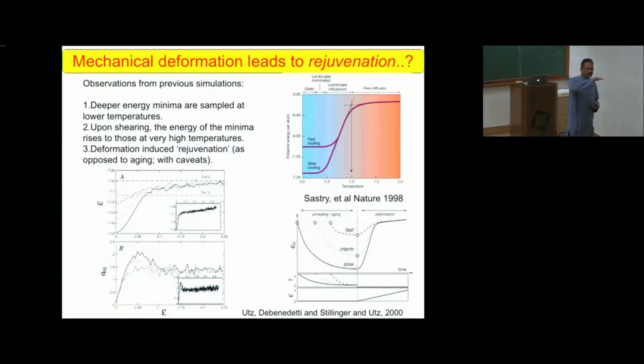So at high temperatures, you're basically sampling something that's referred to as the top of the landscape. These are the worst possible glasses you could make by taking a high temperature liquid and doing an infinitely fast quench. But as you go to lower and lower temperatures, you anneal the system so that even when you do an infinitely fast quench, you're finding energies that are lower and lower, okay?